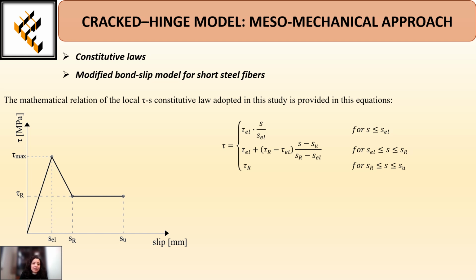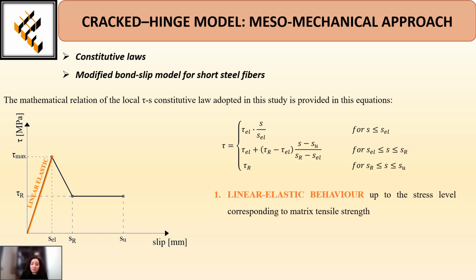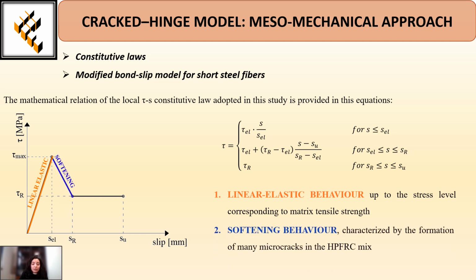In the end, as regards the constitutive law for the short steel fibers, the mathematical relation of the local constitutive law adopted in this study is provided in this equation, where s was considered equal to the crack opening displacement at the level of kth fiber, while the 5 unknown parameters have to be calibrated using the experimental data. In particular, the nonlinear bond-slip law is divided in 3 different branches: a linear elastic behavior at the stress level corresponding to the matrix tensile strength, a softening behavior characterized by the formation of many microcracks in the mixtures, and a constant behavior.